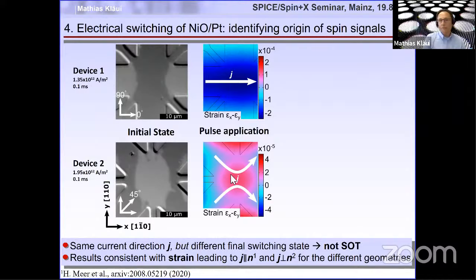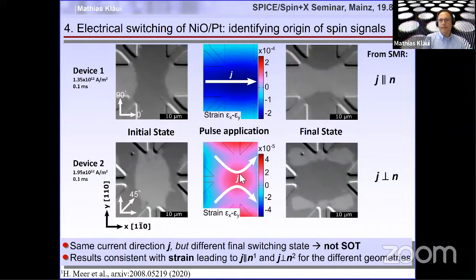But as we can see from the heat and the strain, there's opposite strain. And we see that indeed the switching has the opposite sign. So we see here the switching of the Néel vector is parallel to the current, and here it's perpendicular to the current. And so this means already it cannot be spin orbit torques.